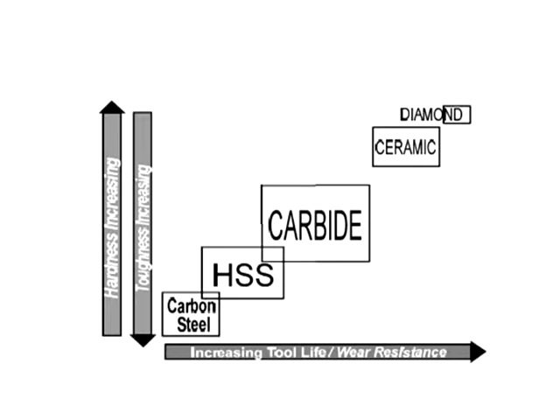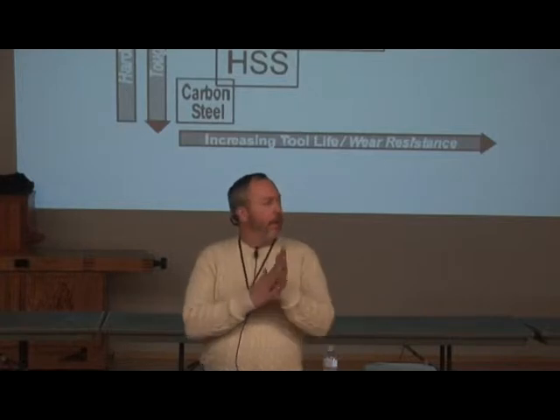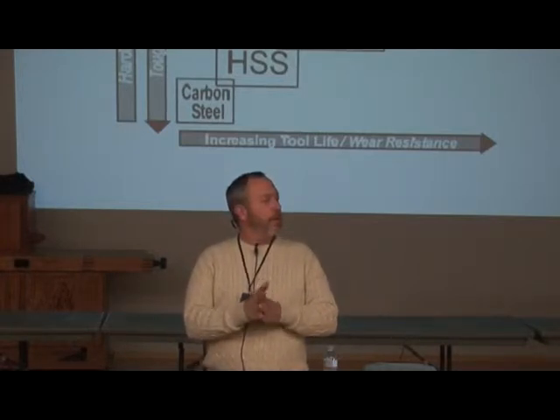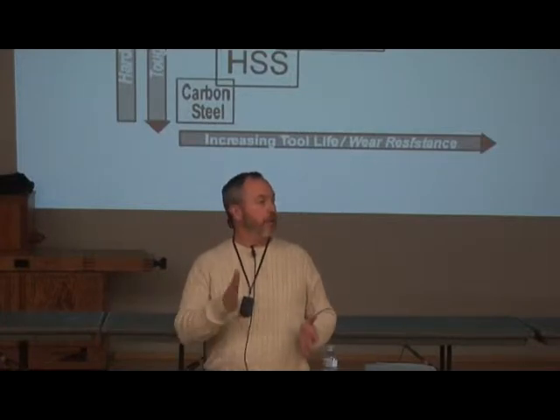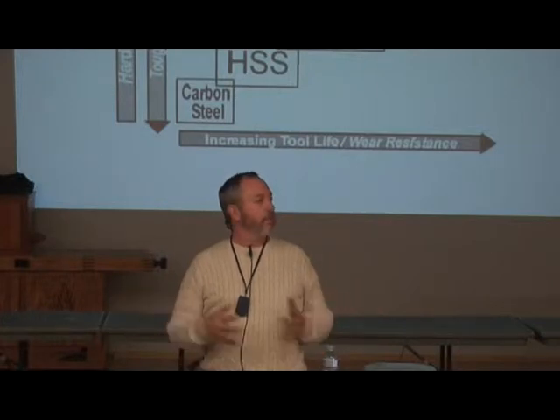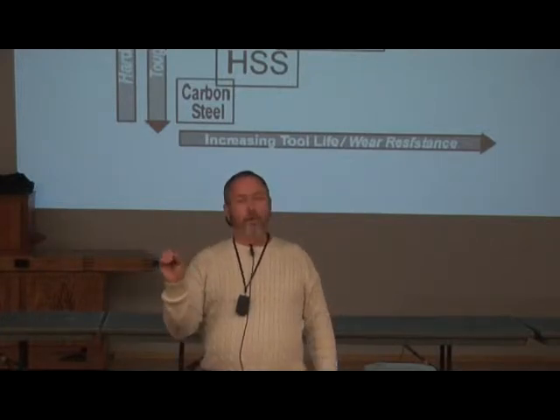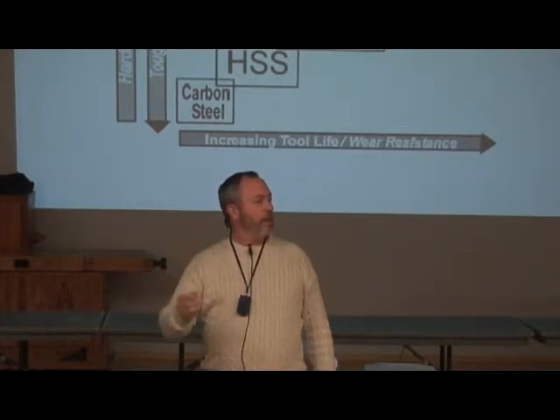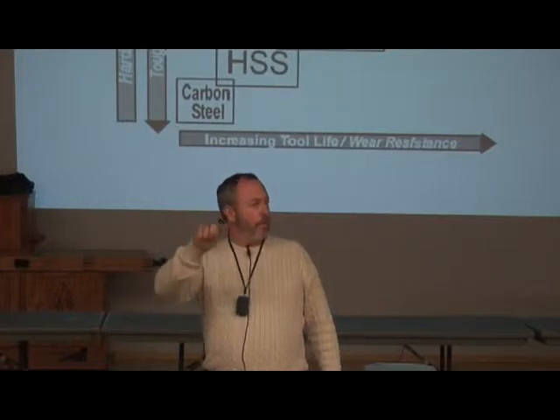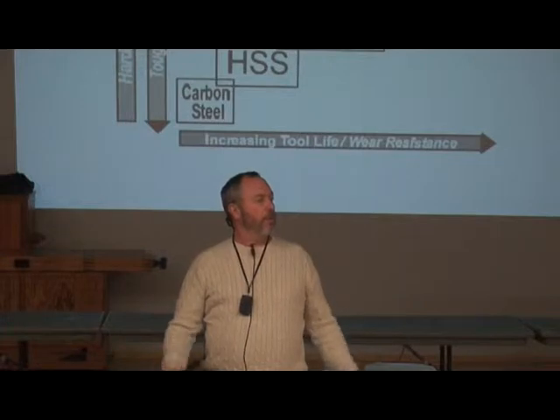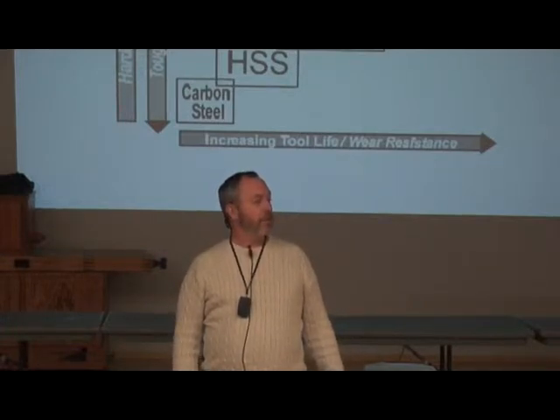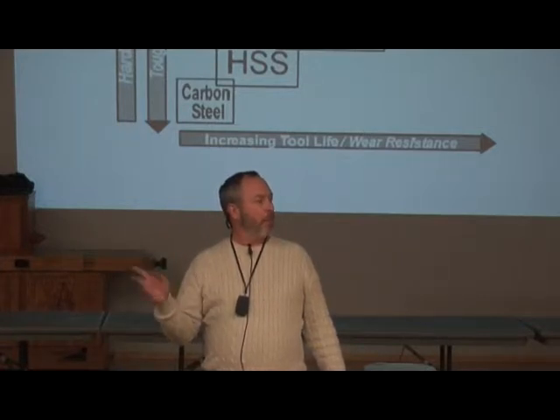Just like nothing. Yes? There's some carbide saw blades on the market, real cheap. There's a carbide, and then you get a $100 carbide blade, you get a $30 carbide blade. Is there a difference in the carbide? Yes. In my lab, I buy carbide blades for cutting hard stuff, like a crankshaft. You can take a bandsaw blade and cut through it, and they're running Rockwell C55. They have different carbide grades for the tips, and the way they grind them, the throat in them, etc., determines the performance of the blade. There's a big difference in price between the grades of carbides on the tip and their performance.